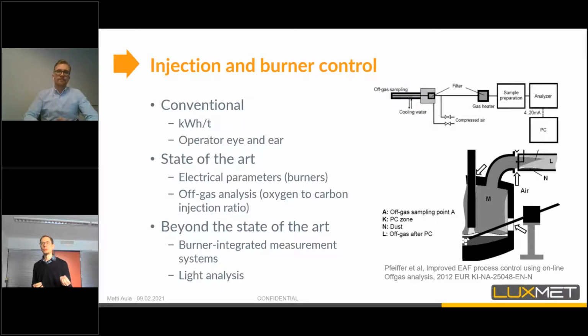And also a very important method nowadays in EAF control is off-gas analysis, because the ratio of carbon injection to oxygen injection needs to be in a certain range, and it's extremely difficult to define this range without knowledge of the off-gas. So with this off-gas analysis feedback loop, we can directly control the injection amounts and rates to get the maximum energy out of the injected oxygen and carbon. And this light analysis can also be used in the timing of, for example, the burners. If you see that the burner flames are already in the freeboard, of course you should not use the burners anymore. It's too late for those.